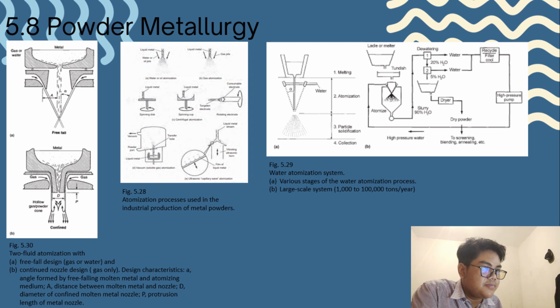Gas atomized powders are typically more spherical in geometry and possess a lower surface oxygen content than their water atomization counterparts. During the gas atomization process, the liquid metal is disrupted by a high velocity gas such as air, nitrogen, argon, or helium that is directed through a specially shaped nozzle. Atomization occurs by kinetic energy transfer from the atomizing medium to the metal. In order to visualize this process, the breakup of the metal stream into fine droplets can be compared to the way that gasoline is atomized as it passes through the venturi nozzle in an automobile carburetor.